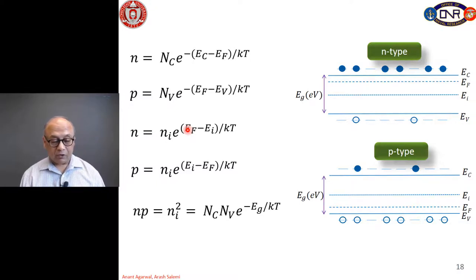An alternate expression for electrons and holes in terms of the intrinsic carrier concentration is also given, where the gap between the Fermi level Ef and the intrinsic level Ei, which is the middle of the band gap, is measured with respect to the electron concentration. And again, as electron concentration increases by doping more heavily, the Fermi level moves away from the mid gap towards the conduction band edge. And similarly for p-type, you can see that the Fermi level moves away from the mid-gap towards the valence band edge as we increase the hole concentration.